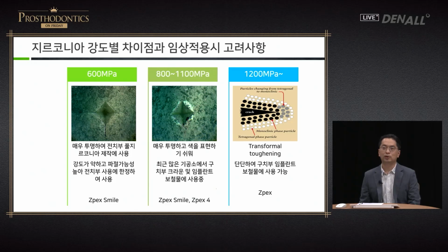This is an image where diamond was used to crack the ceramic to measure the strength and to observe how the crack progresses. You can see that in 600 megapascal, the crack has fully progressed. The transformal toughening does not exist in cubic zirconia, and therefore, it can be fractured and the strength is not really strong. Tosoh zirconia powder is used frequently for fabrication. In the case of 1200 megapascal zirconia, Z-Pex is used. For 800 to 1100 megapascal zirconia, Z-Pex Smile and Z-Pex 4 are used.